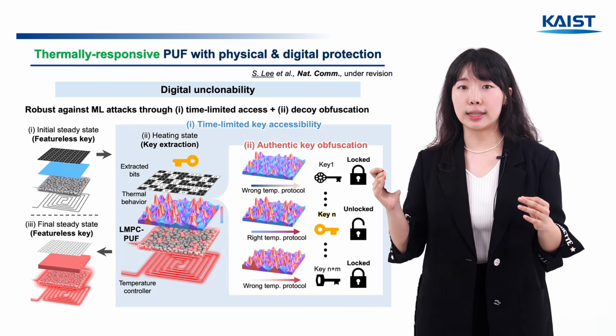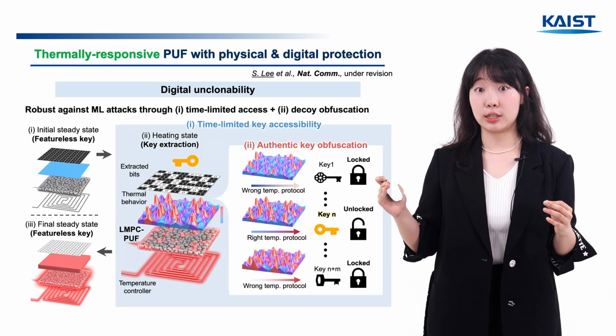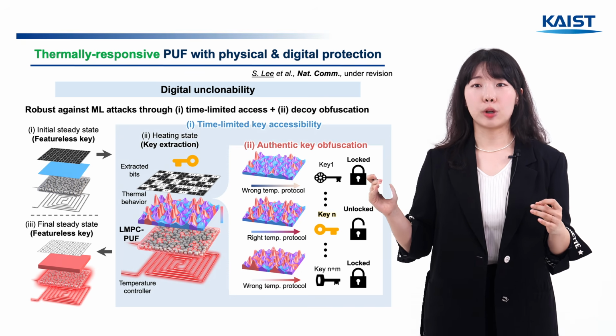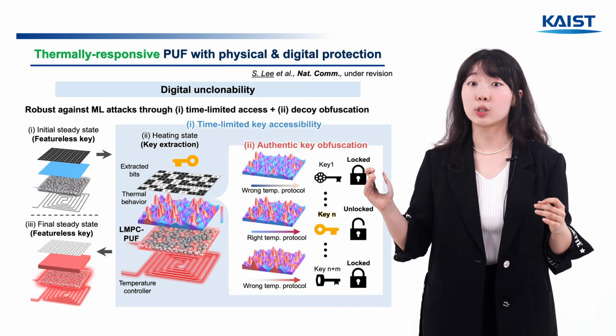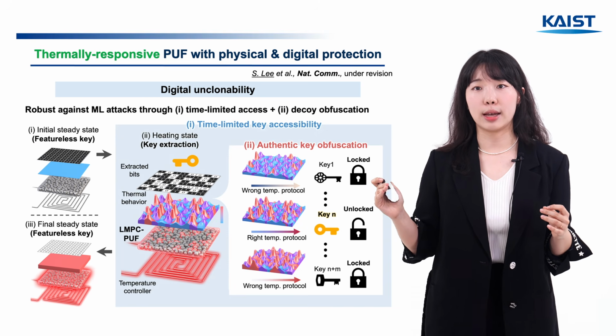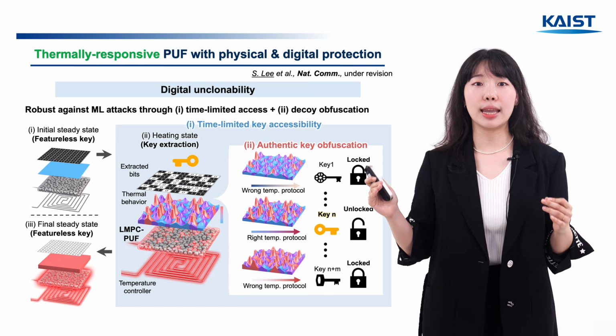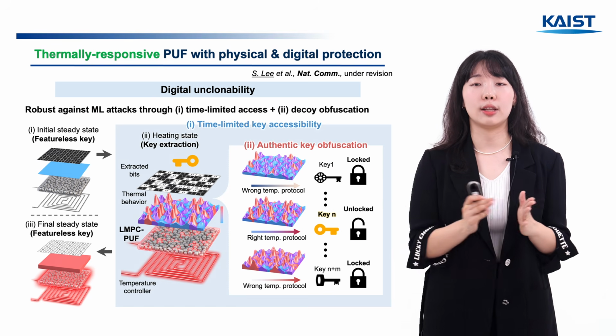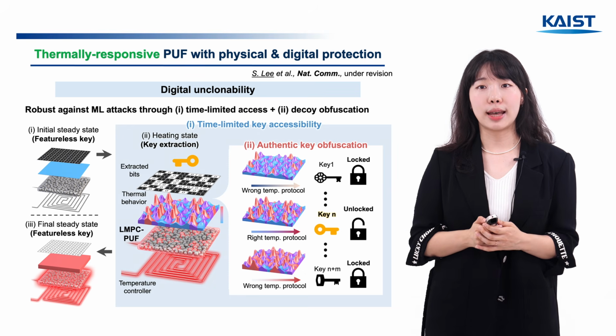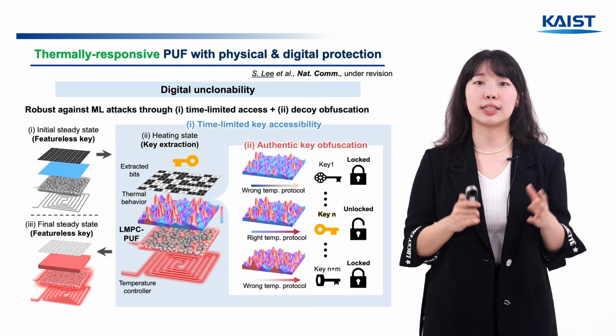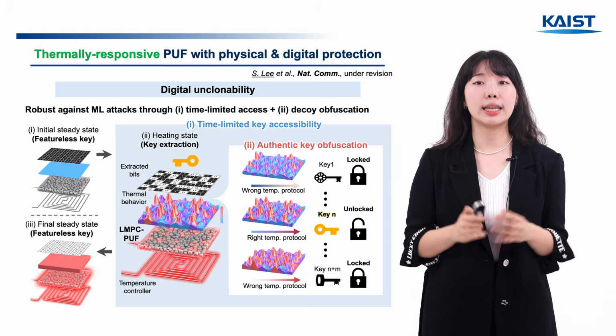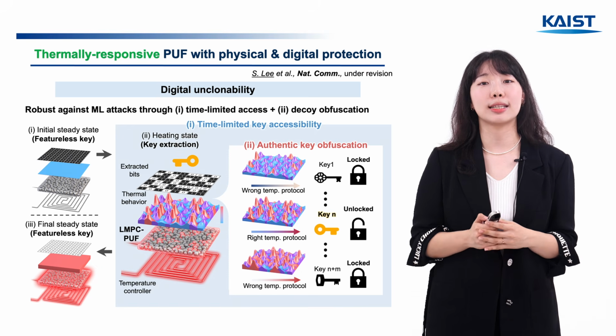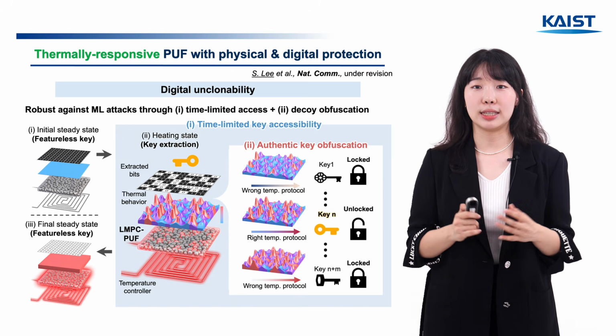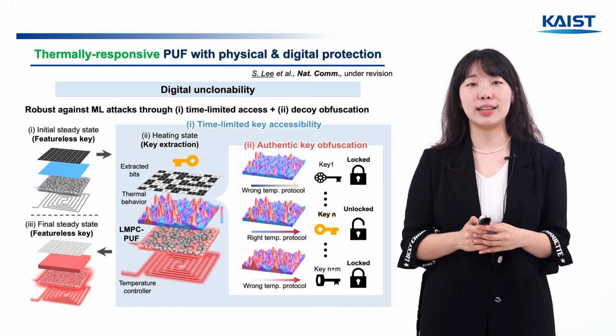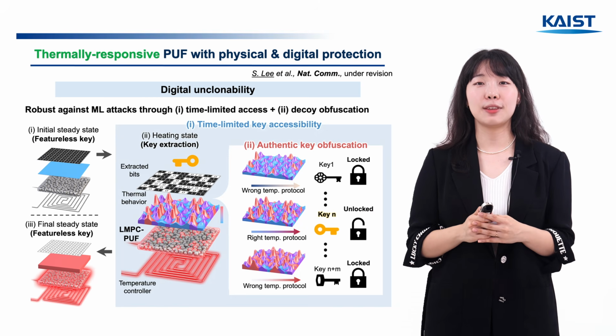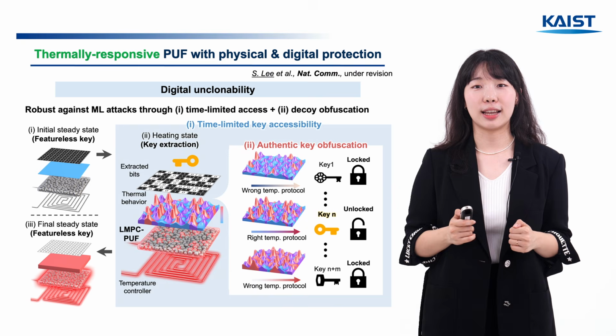Once it reaches the end temperature and settles into thermal equilibrium, the particles are at the same temperature, so once again, no meaningful key comes out. This means CRP data can only be collected during the limited window. On top of that, the key changes depending on the starting temperature, so without knowing the exact temperature protocol, you cannot tell the real key from the disguised one. These two mechanisms together form an effective defense against machine learning attacks.